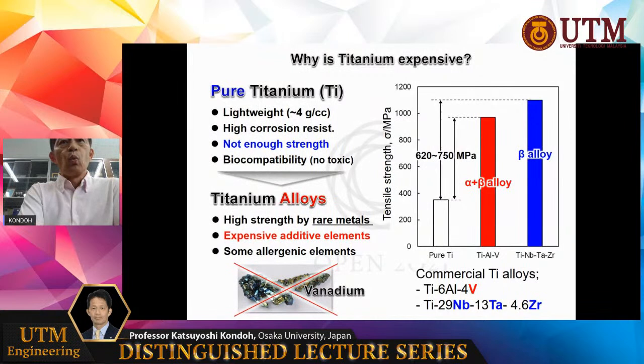So why is titanium expensive? Of course, pure titanium is not so expensive. However, as shown in this graph, pure titanium has a very low strength compared to titanium alloys. So to improve the strength of pure titanium, we must add alloying elements. In that case, as shown here, very expensive rare metals must be added to improve the strength, for example, vanadium, niobium, tantalum, or zirconium. Of course, as a result, titanium alloys show very high strength with low density. However, titanium alloys are very, very expensive.